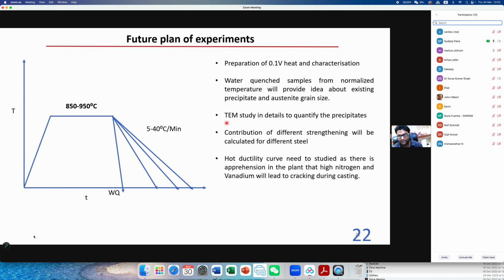And we will do extensive TEM study, and also water quenched samples we will be studying to get the idea of what type of precipitation is there at that time, and during cooling, what type of precipitate, what is the amount of precipitate we are observing, and then we will calculate the contribution of different strengthening mechanisms. The industrial partner JSPL wants to have a hot ductility curve for this high vanadium nitrogen steel, so that they can easily cast.